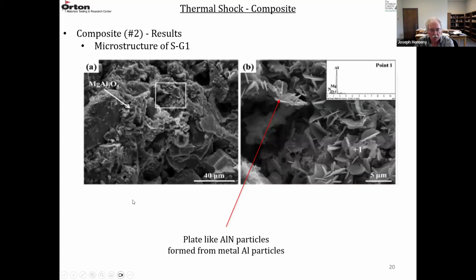So when they looked at the microstructure, this is SG1. These are fracture surfaces. They're just pointing out these minor phases that are present. This is the spinel MgAl2O4. So there's some spinel forming on some of the MgO particles. And then this square is this photograph at higher magnification. This is a 40 micron bar. This is a 5 micron bar. So you see these little flakes that are forming at high magnification. They did an EDS analysis on those, and it's basically aluminum and nitrogen. So these flakes are plate-like particles of aluminum nitride that are forming from the aluminum metal.